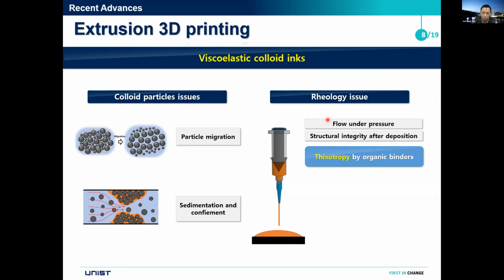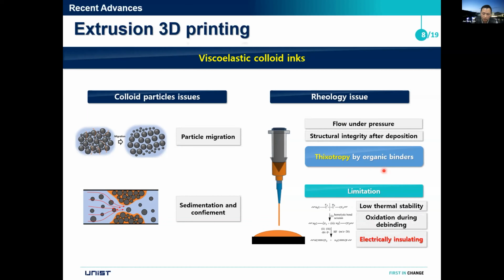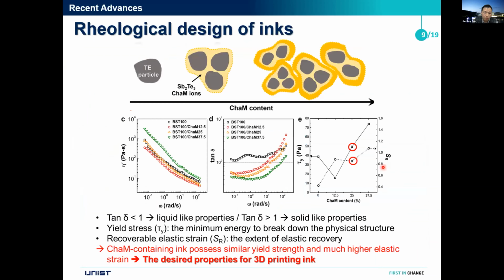Such a rheological property is called thixotropy, which is easily achieved by organic binder addition. However, the organic binder has some critical limitations, such as low thermal stability and oxidation, and most importantly, these are electrically insulating. So our group has designed particles by introducing some negative ions on the surface of the particle, which generated a charged thermoelectric particle.